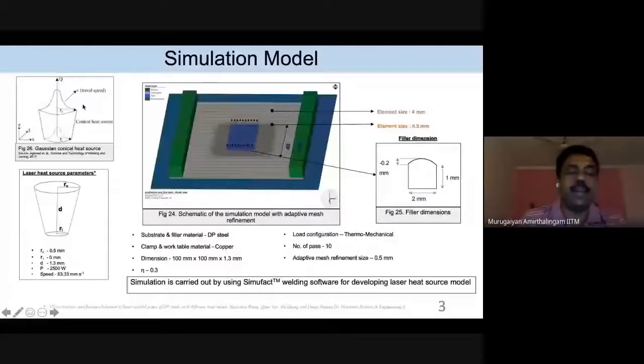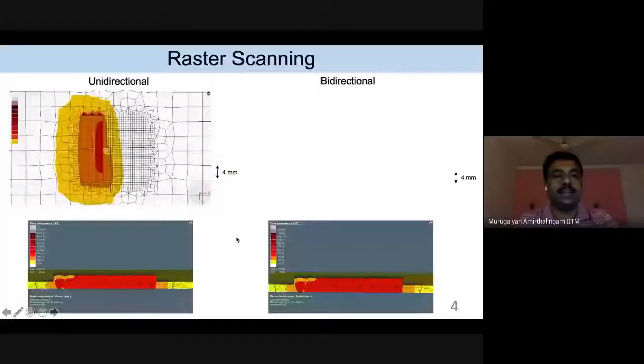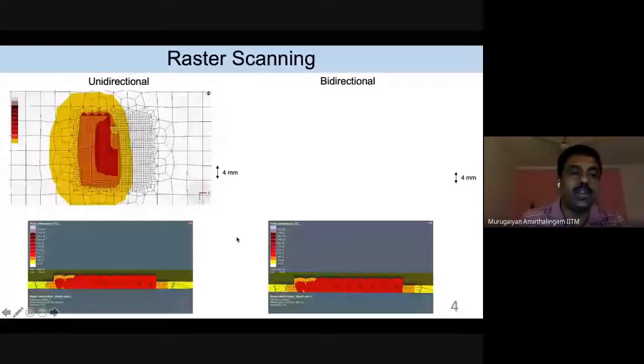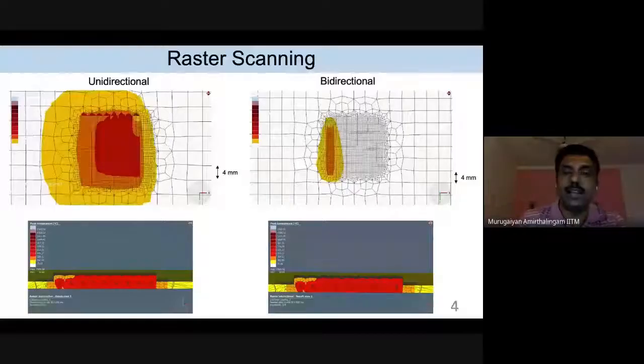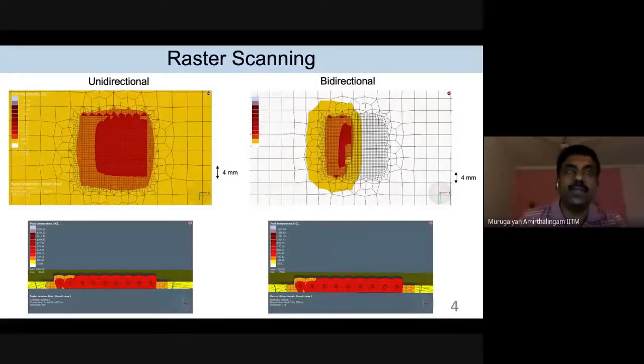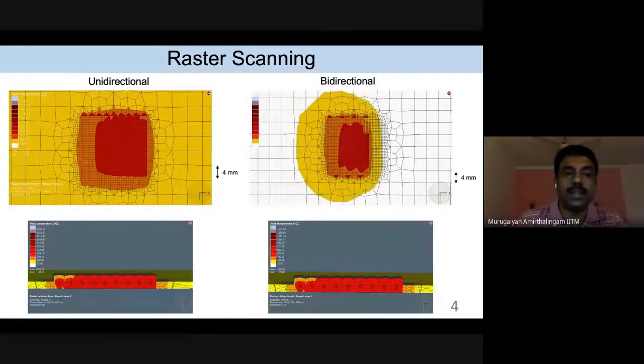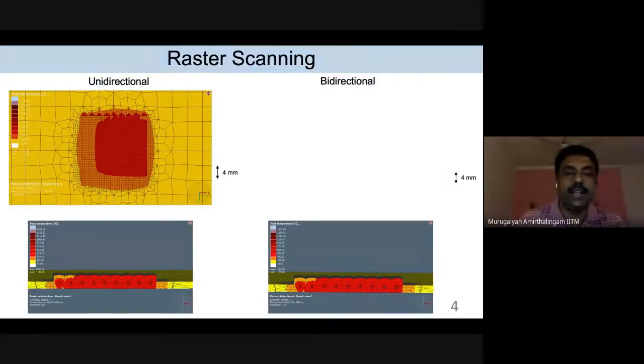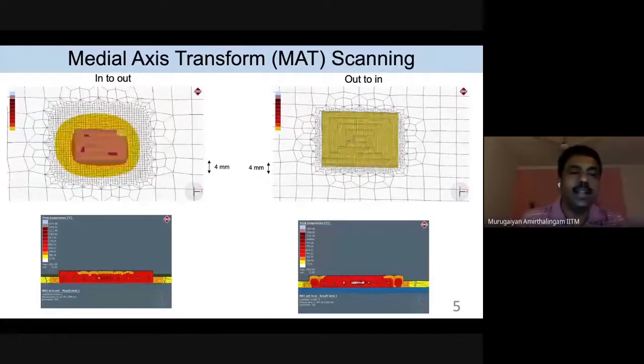This is actually used for a laser deposition process, DED process, where we have a heat source model, and then we can optimize the path. And during this deposition, you can identify, for example, when you do unidirectional deposition, how the heat is actually accumulated, and when you do unidirectional, bidirectional deposition, how the heat transfer affects the temperature distribution of the bead, right? So that can be calculated based on the thermophysical properties and the boundary conditions. And you already see that there is an effect instead of using a simple uniaxial and bidirectional raster scan, if you use an in and out medial axis transformation.